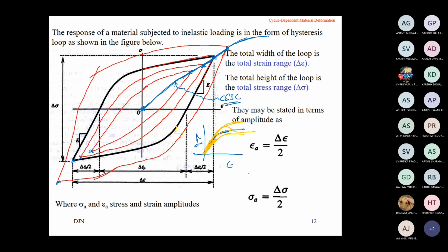With every cycle of load, the material is getting strain hardened. If the curve is initially high and then decreasing, what does it mean? For an initial number of cycles, the material shows strain hardening behavior. After covering a particular number of cycles, the material starts to soften by itself under the applied loading.